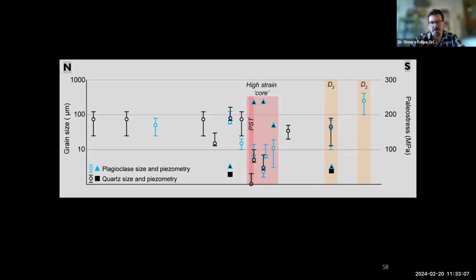And especially where the pseudotachylites are, when you're measuring the stuff right next to the pseudotachylites, within a few inches of it, you get some really, really fine-grained stuff. So this observation of grain size reduction, probably correlating to higher differential stresses, bears out when you do a really rigorous field measurement of it all.